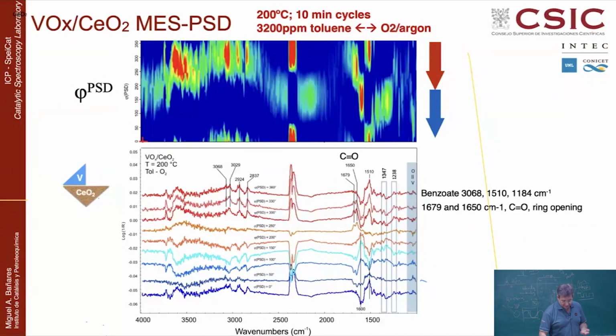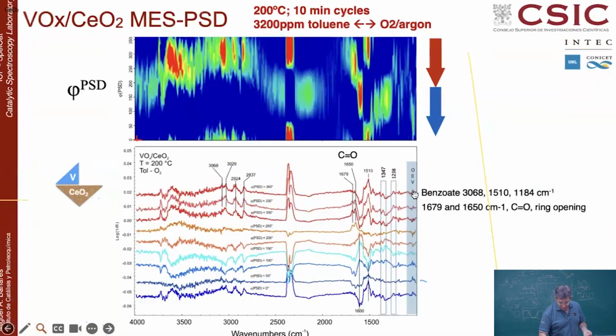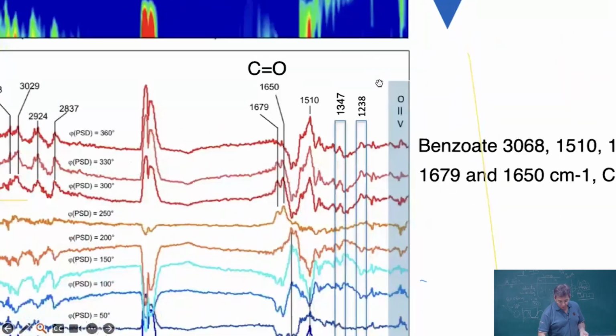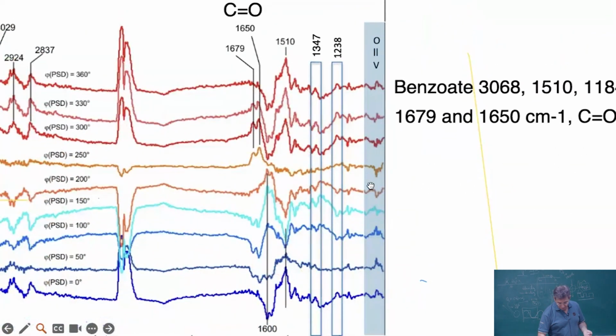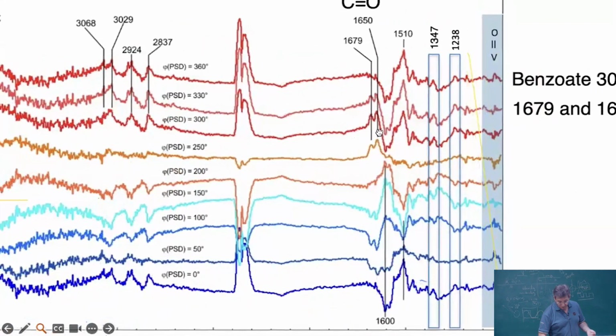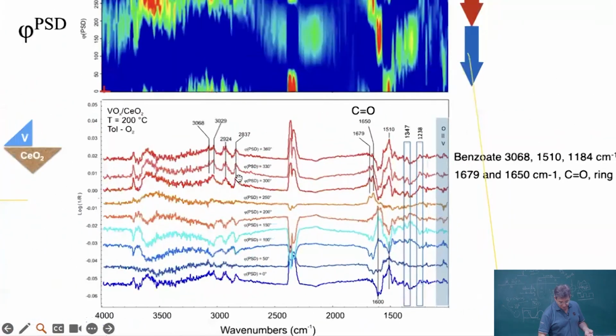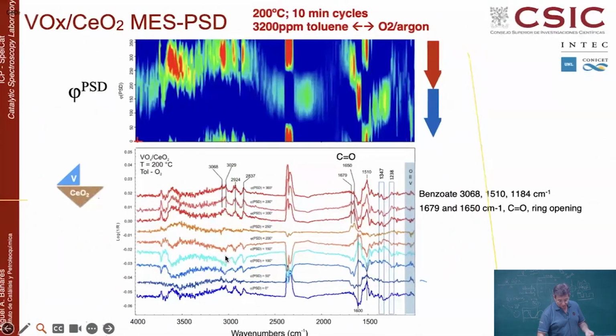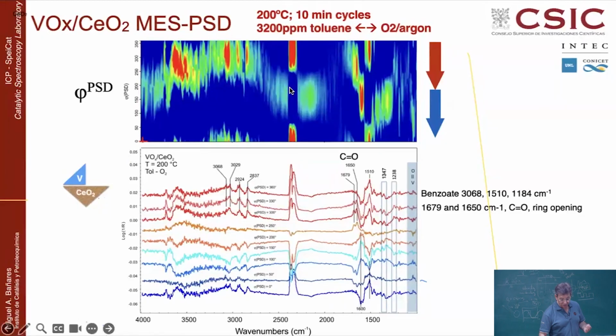And that was for ceria. In the case of vanadium ceria, which is slower, like for instance here, you can see the vanadyl mode. The vanadyl group, you see it decreasing, goes negative when you are feeding the toluene, and then when you take the toluene off, you see it being reoxidized. So this is the vanadyl group, but also you can see a carbonyl species from the oxidation. So you can see a lot of things coming in and out. Even the formation of CO2 is relevant, because atmospheric CO2 that you get in the infrared spectra doesn't respond to your perturbation. So the CO2 that grows and decreases here is the one that grows and decreases with your perturbation. So this CO2 is part of the reaction. It's not environmental CO2, which is also important.